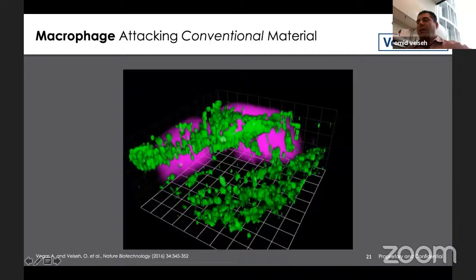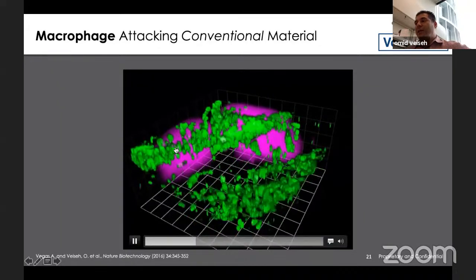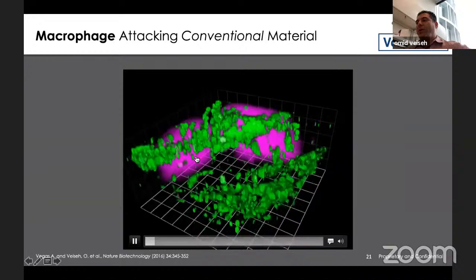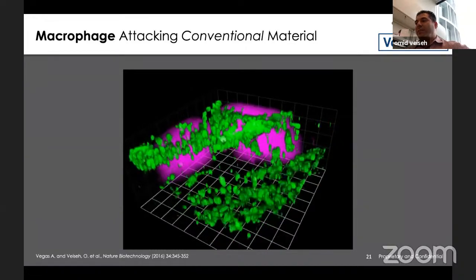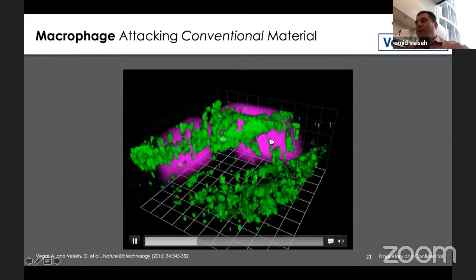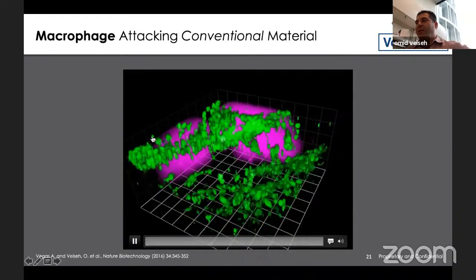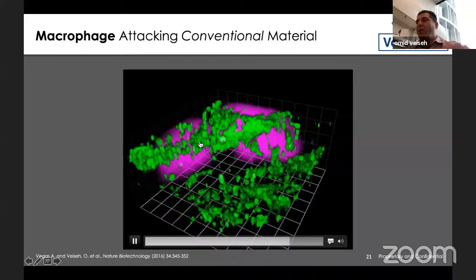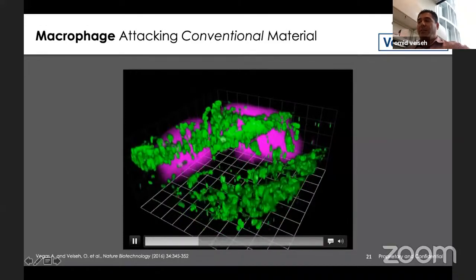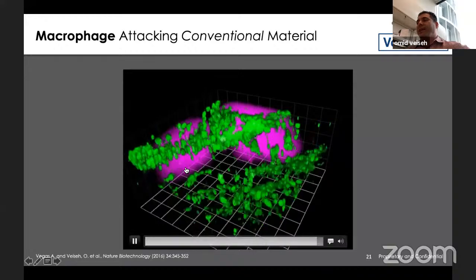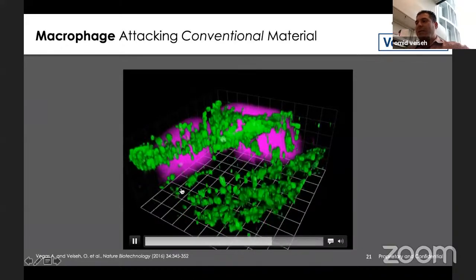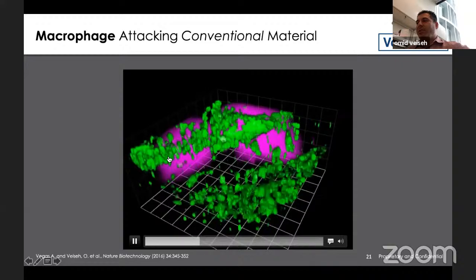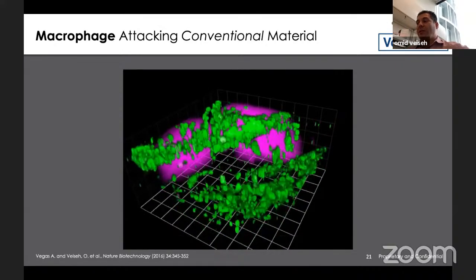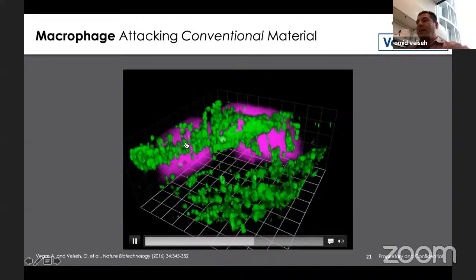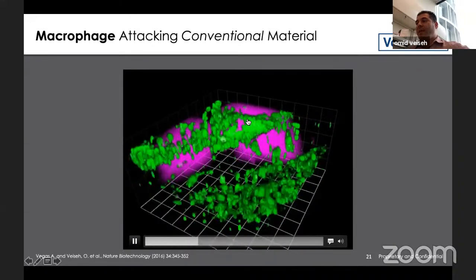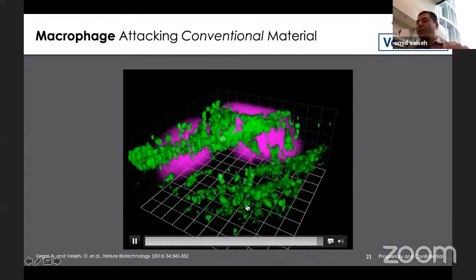So we wanted to understand why we're getting these impressive results. We did this study in mice where all the macrophages express green fluorescent protein. This is in the intraperitoneal space. Our implants are in magenta, and in this case, they're unmodified. We evaluated how the immune cells perceived the implants using this technique. This is about 6 hours of imaging that's been condensed to a 30-second loop. One of the things that we notice is there are quite a lot of immune cells there when there's an unmodified material. The immune cells have adhered to the implant, and they have recruited additional immune cells to come in.